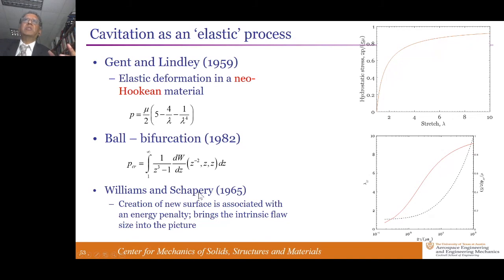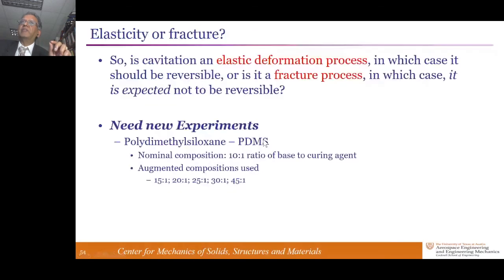So we did experiments on the same material. Dow Chemical seems to make something that's very consistent over decades. With the nominal composition that everybody uses, we also recognize that you could play with this elastic stiffness and the stretchability of the polymer by varying the composition to non-recommended stoichiometric cases. And what this means is at a 45 resin to 1 catalyst, there are fewer crosslinks in the material than in the nominal 10 to 1. And therefore, it's going to exhibit much more stretching before it starts to stiffen up.